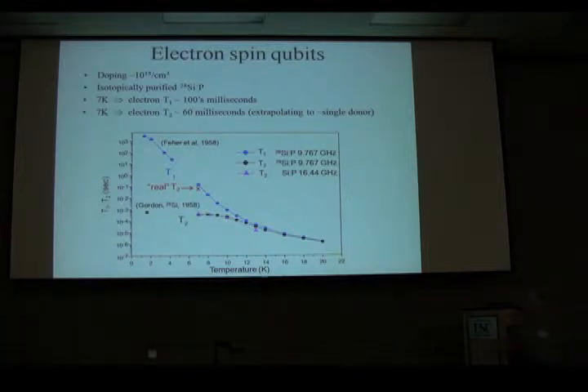Jim had just finished as a graduate student building the first maser. And he went off to Bell Labs and made a maser out of phosphorous doped silicon. But interestingly, when he did that, he got a T2 down here a little below a millisecond. And when we first started working on this, here's some data. These are T2 measurements. We did it at a couple different frequencies. And everything seemed to saturate just about where Jim got it. So we came along 50 years later and thought, alright. You know, now we have fancy new machines. Jim had to build his own system. We were going to be able to get a long T2. And we ended up saturating just about where he did.